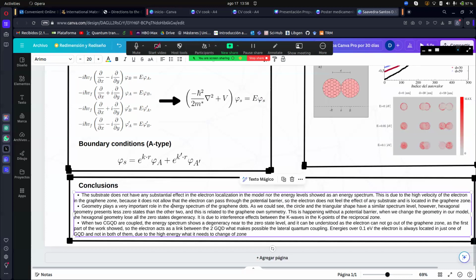We can also say that when two circular graphene quantum dots are coupled, the energy spectrum shows degeneracy near the zero state level, and it can be understood as the electron cannot go outside the graphene zone, as the first part of the work showed. So the electron acts as a link between the two graphene quantum dots, which makes possible the lateral quantum coupling. For energies over 0.1 electron volts, the electron is always located in just one of the graphene quantum dots and not in both of them, due to the high energy it needs to change dots.